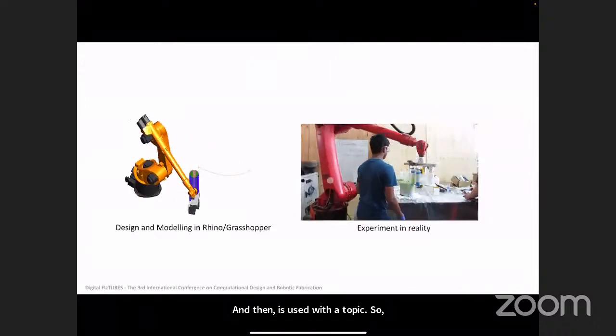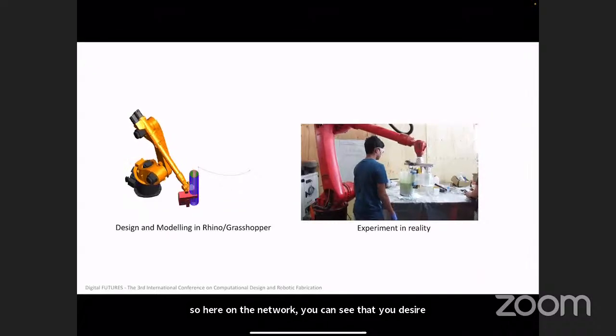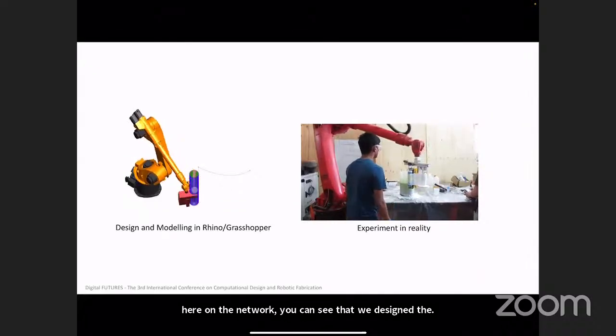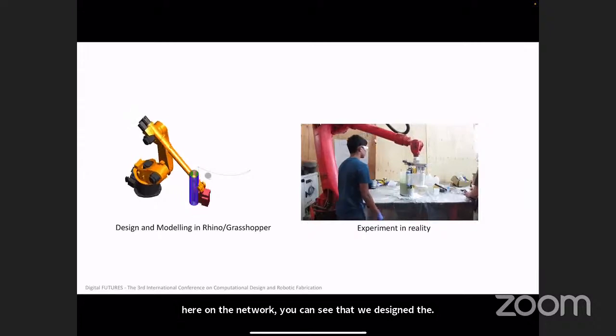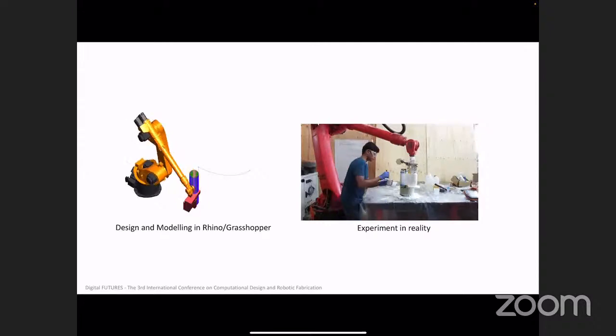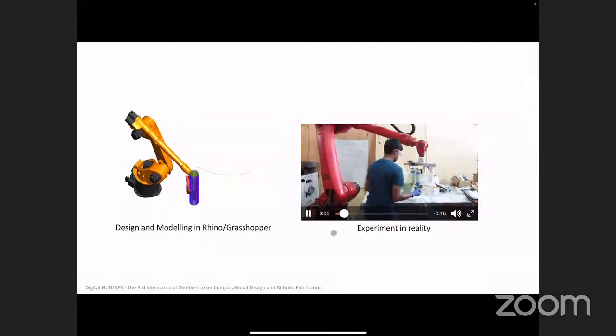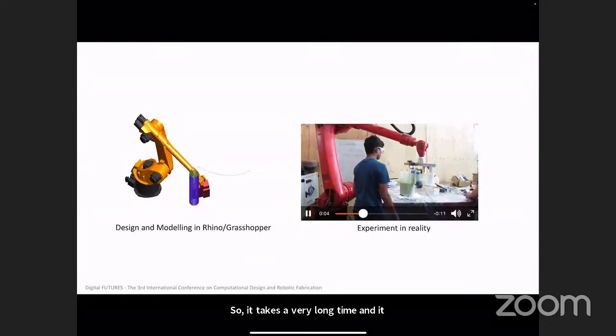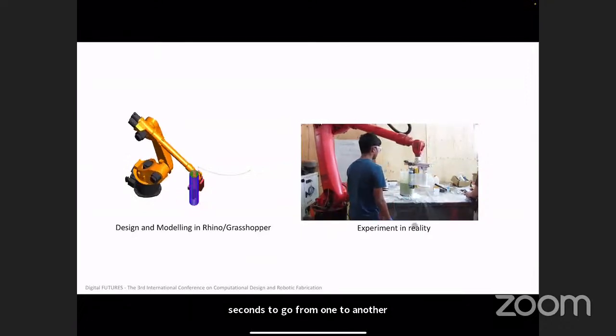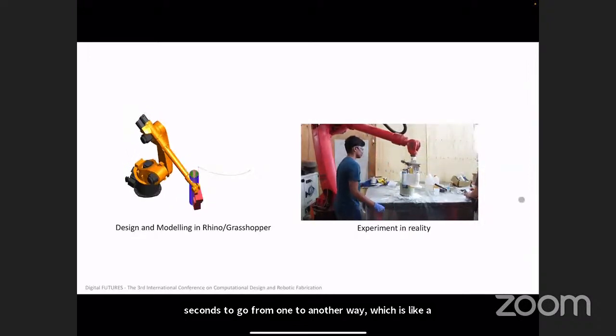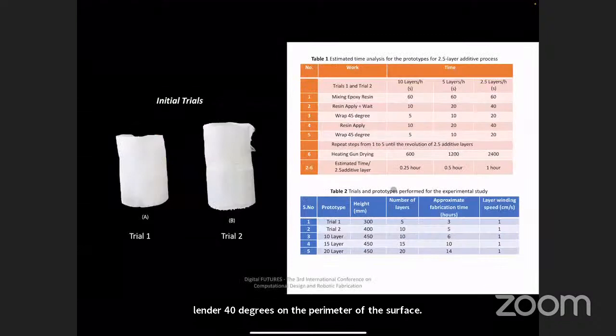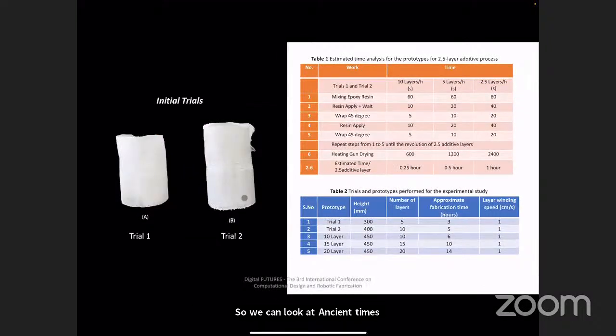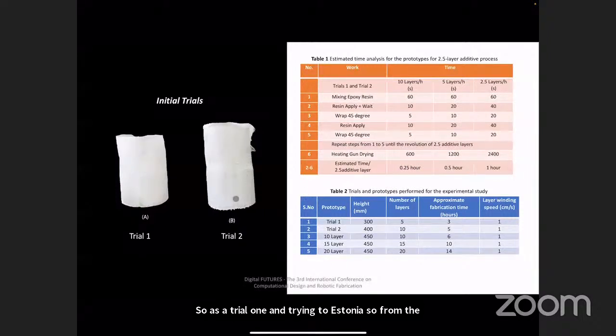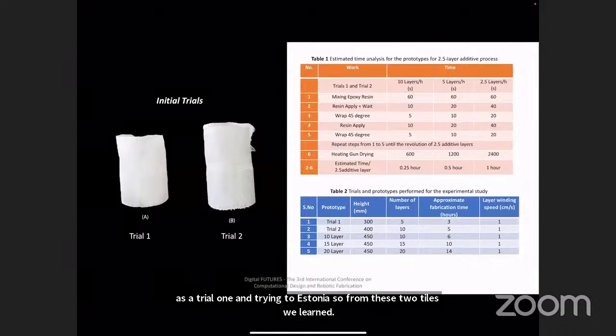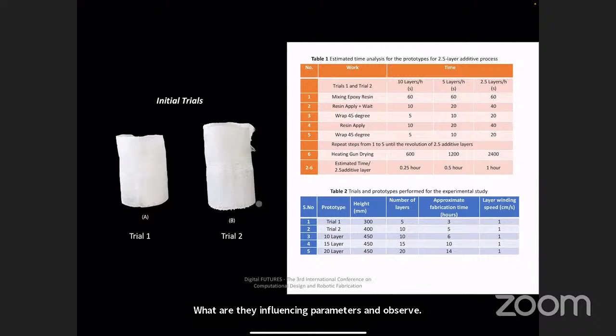Here on the left, you can see that we designed the KUKA robot and the modeling, which is shown in a GIF image. But in reality, it takes a very long time to apply the epoxy, and it takes around 20 seconds to go from one end to another, which is a wrap of 45 degrees along the perimeter of the surface. So we conducted initial trials, trial 1 and trial 2 as shown here. From these two trials, we learned the influencing parameters and observed what factors we need to control so that we can get good trials.